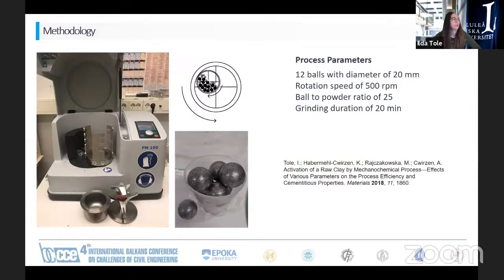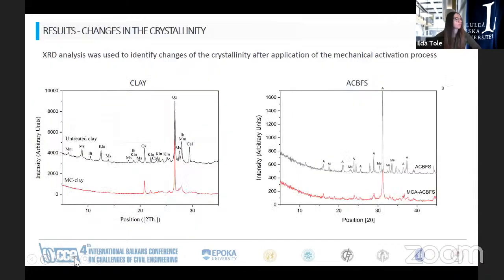Different parameters can be changed to achieve different types of activation. Actually, another study was done on the optimization of these parameters, and in the study case that I'm presenting, I'm just utilizing the optimized process parameters that I found previously. So in this case, a fixed rotation speed of 500 rotations per minute, a ball to powder ratio of 25, and a grinding duration of just 20 minutes. Both clay and air-cooled blast furnace slag were treated with this process.